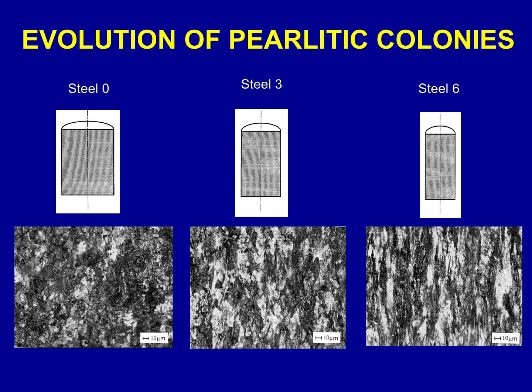The evolution of the first microstructural level of pearlitic colonies from steel 0, 3 and 6, representing steel wires with 0, 3 and 6 drawing steps. We see in steel 0 a randomly oriented microstructure regarding pearlitic colonies, a small orientation in steel 3, and a very marked orientation after heavy drawing in steel 6, in which the colonies are markedly enlarged, slenderized, and oriented in the vertical axis, y-axis, or cold drawing direction.